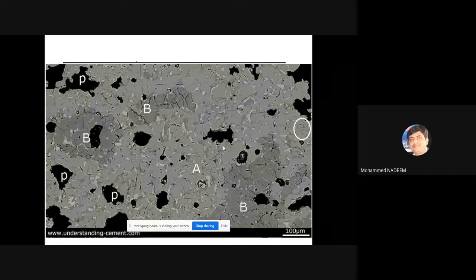This is a real picture of a concrete taken through the SEM, electron microscope. Size is 100 micron. Just for understanding, human hair size is 80 micron. This line, if you see right below, is 100 micron. So the black part which you are looking at is nothing but fine pores. It happens because of evaporation of the water, and if leaching happens because of calcium hydroxide, this is very harmful. Of course, from the naked eye, it's very difficult to see these fine pores, but they are always present in your concrete.